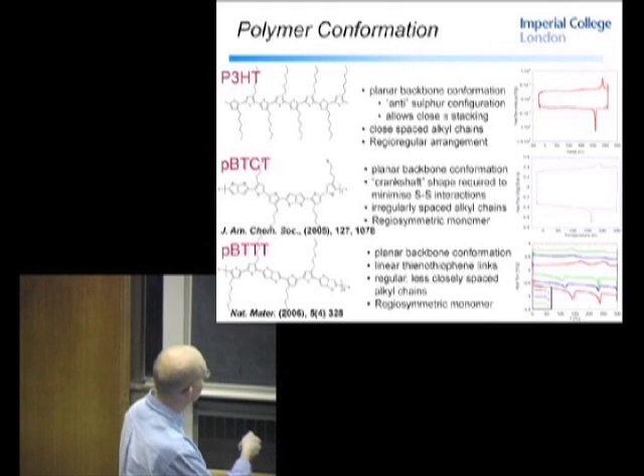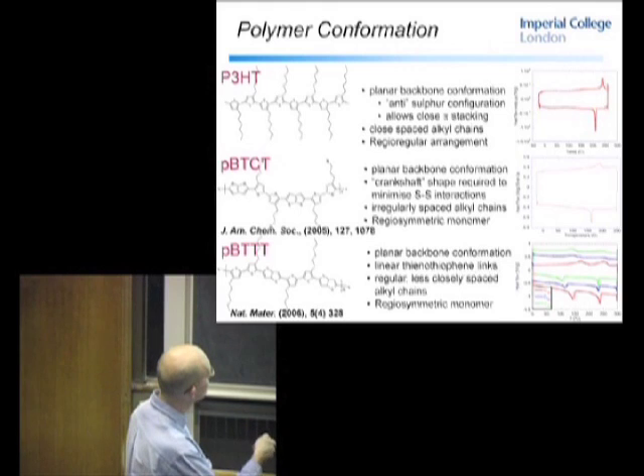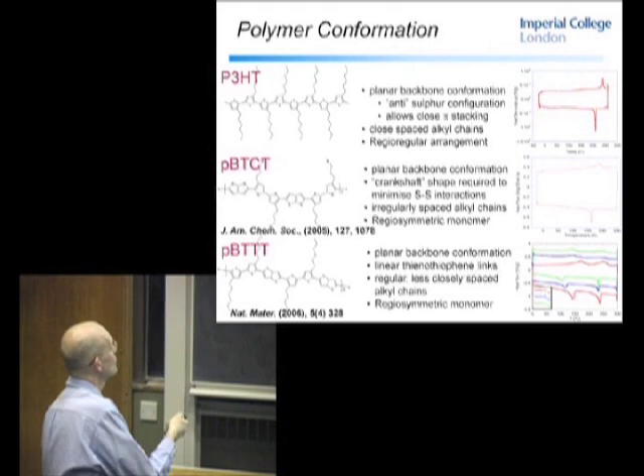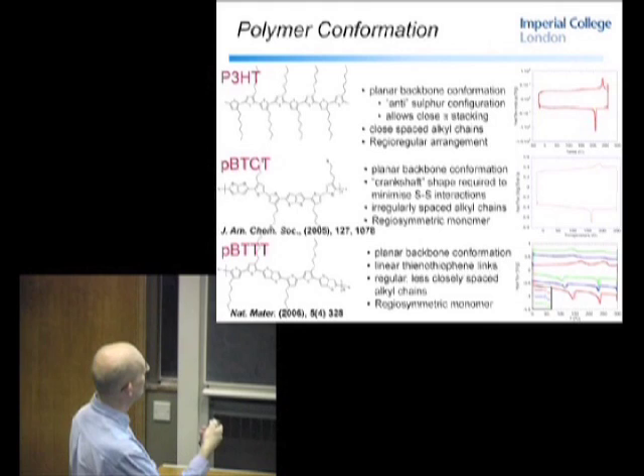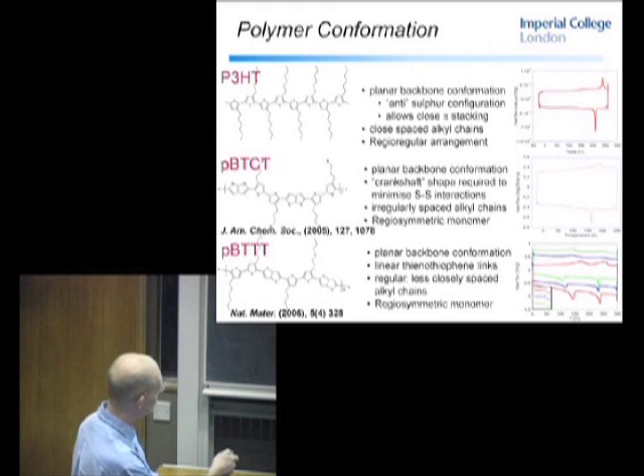Other differences here is that the physical distance between the alkyl chains is larger than in the case of P3HT. I'll talk about the reasons, or the influence that has on properties, later. But also it's a regular spacing, whereas in the case of pBTCT, you see you have this irregular. On the one hand, you have a short spacing and a longer spacing here, shorter spacing here. So there are things you can do, and they all play an important role.